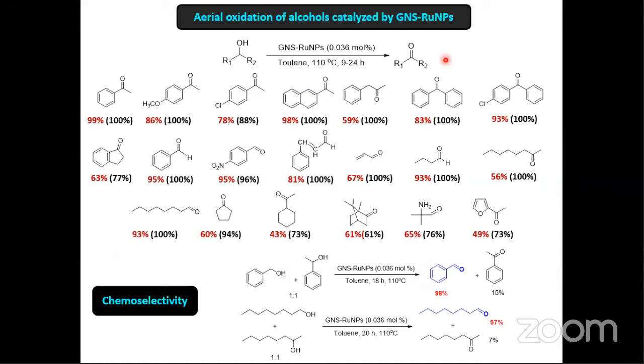And again, in the previous oxidation reaction, we employed a copper catalyst for the same reaction, but there periodic acid was required as an oxidant. But here, you look at this reaction, there's no oxidant, right? You have catalyst, you have solvent, temperature, only time. What is the oxidant here? The oxidant is air. Now you perform the reaction in air atmosphere. So the oxygen present in the air can act as an oxidant and catalyze the oxidation of alcohol in the presence of ruthenium nanoparticle. Very interesting.